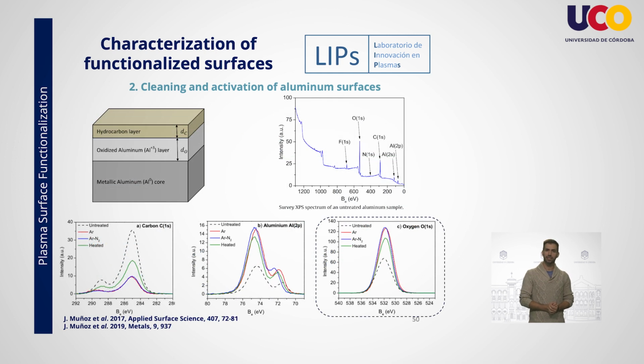To check this, the samples were analyzed using XPS. According to XPS, the untreated surface is composed of aluminum, oxygen, carbon, and fluorine. The intense oxygen signal suggests the presence of an oxidized aluminum layer below an external hydrocarbon layer, whereas fluorine and carbon are related to the processing of aluminum foils.